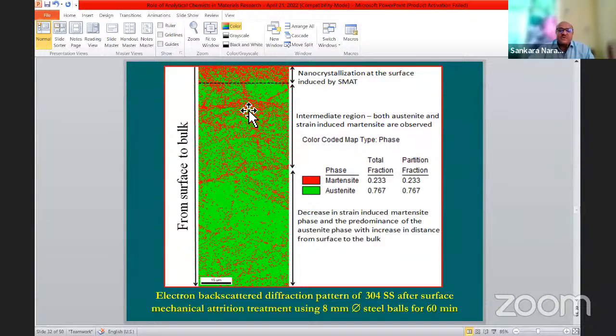During this impingement, generally stainless steel is austenite phase. Austenite phase will be very high generally. But when you do an impingement using steel ball, there will be a phase transformation from the austenite phase to the martensite phase. So using electron backscatter diffraction pattern, we can quantitatively determine how much phase is transformed. This is the area where the transformation is maximum, in the nanocrystallized area, and with increase in depth from the surface to the bulk, the extent of martensite formation decreases continuously. So we can calculate up to what depth martensite formation is there, and how much volume fraction.